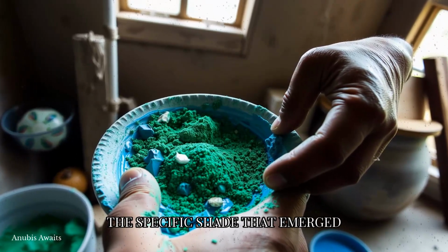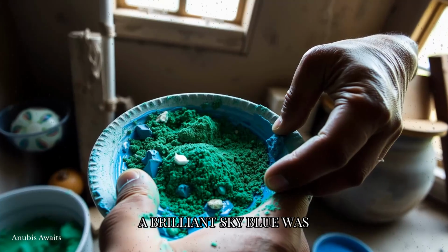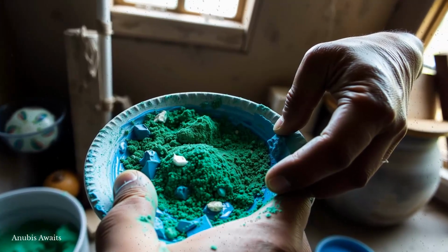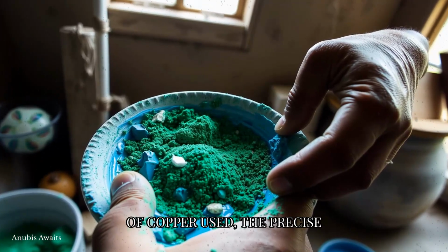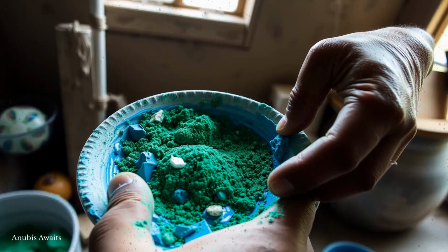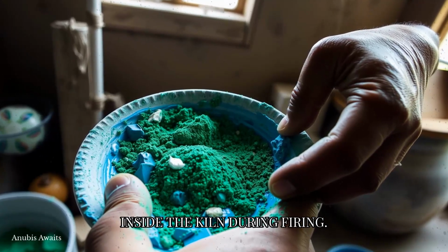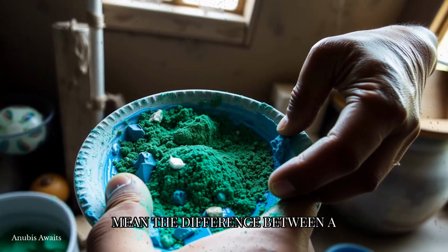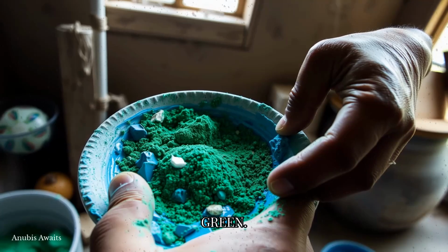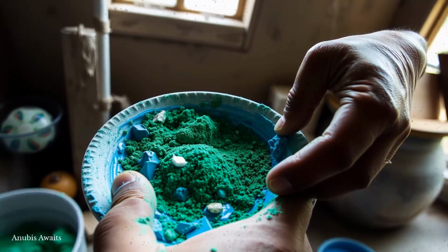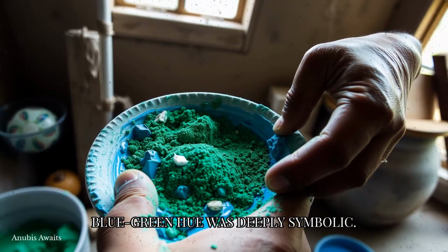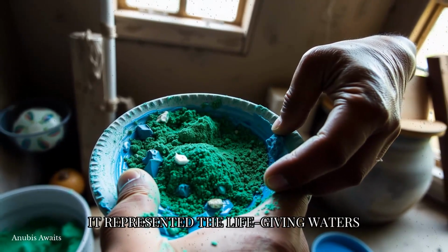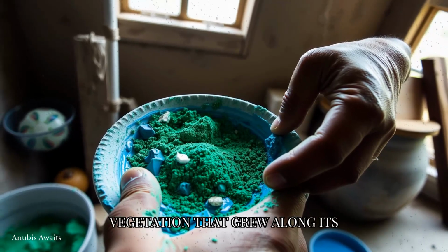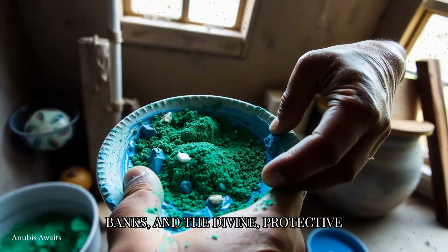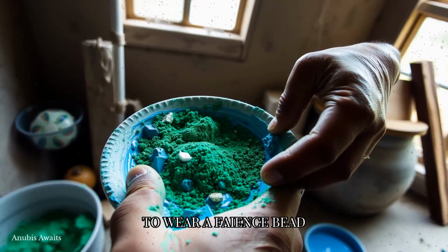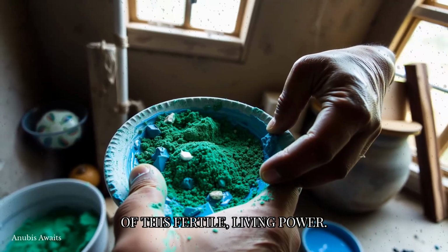The specific shade that emerged, from a deep turquoise to a brilliant sky blue, was a delicate dance of chemistry. It depended on the amount of copper used, the precise mix of other ingredients, and even the level of oxygen inside the kiln during firing. A slightly different atmosphere could mean the difference between a rich blue and a muted green. This was not a random color. For the Egyptians, this specific blue-green hue was deeply symbolic. It represented the life-giving waters of the Nile, the lush vegetation that grew along its banks, and the divine, protective sky arched overhead. To wear a faience bead was to carry a piece of this fertile, living power.